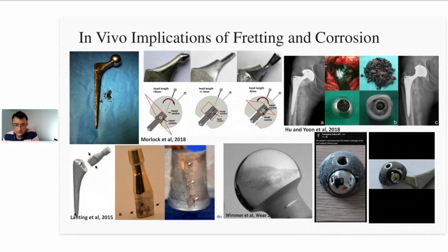And what do these things look like? Well, nine times out of 10, when you take a device out of the body, they don't look pristine. They tend to come out covered in black gunk, oxide layers on the surface. Demonstration of severe corrosion at these interfaces. Through to severe wear in some cases where you see complete material loss and wear down of these modular taper interfaces. But ultimately, when you see an adverse reaction to metal debris, the surgeon is presented with a massive black gloop when they open the joint capsule, followed by a load of dead tissue, which they ultimately need to excise, resulting in more invasive surgery to the patient.